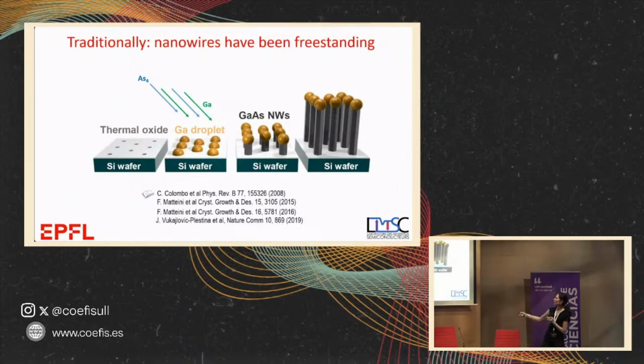So when we send the atoms here, like for gallium arsenide, we would send arsenic and gallium, the atoms will stick inside the holes, but they will not stick on the oxide. They really don't like it. The oxide is really a repellent for that. So if they're right there, they will walk around until they find this place here, and then they create the solid. If you have gallium, you will alloy it later with arsenic, creating gallium arsenide.